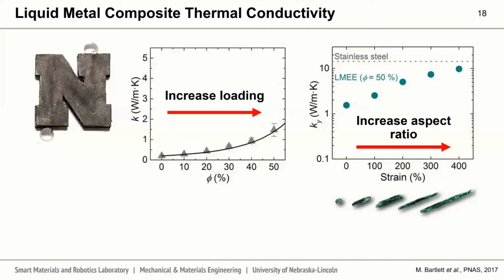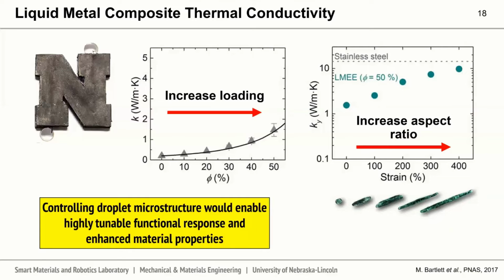However, at this point the only way we can actually achieve a change in aspect ratio is through mechanical stretching, which ultimately leads to programmability in only a single axis. We see that controlling droplet microstructure would enable highly tunable functional response and enhanced material properties if we could spatially control that throughout an elastomer composite.